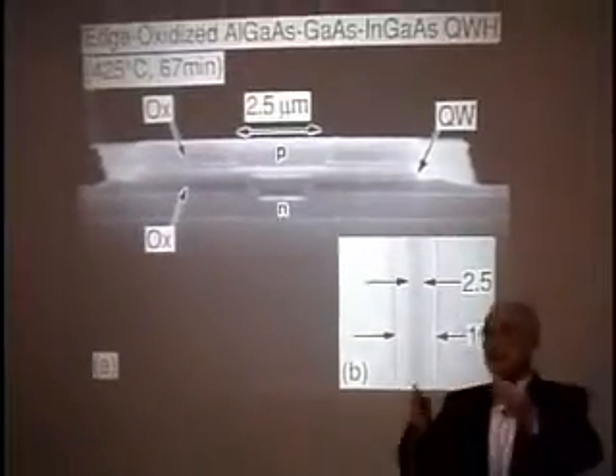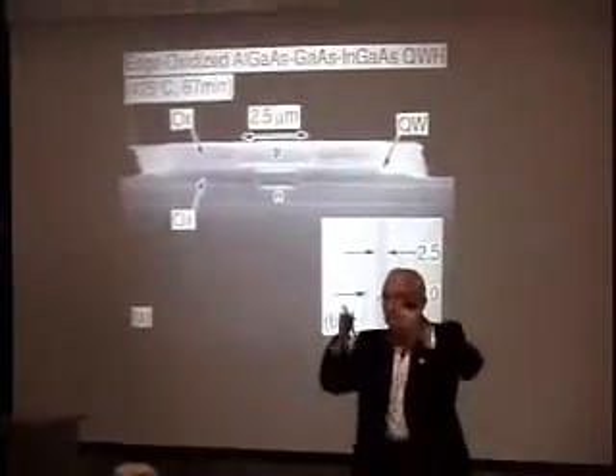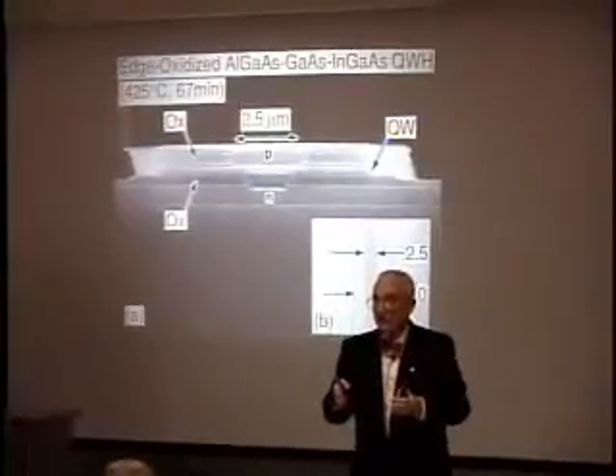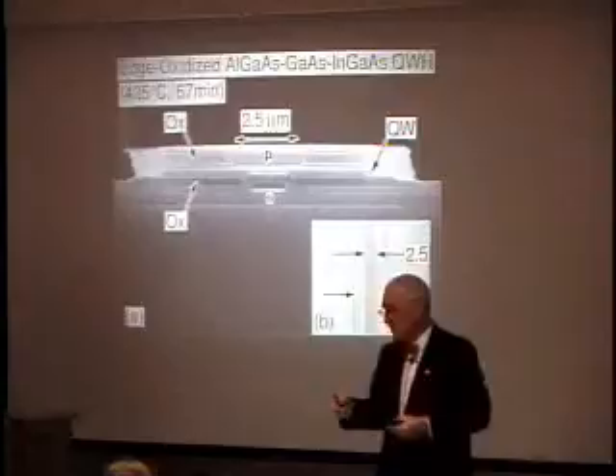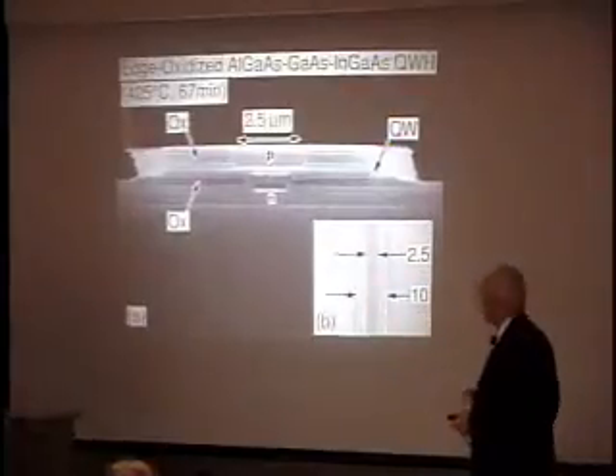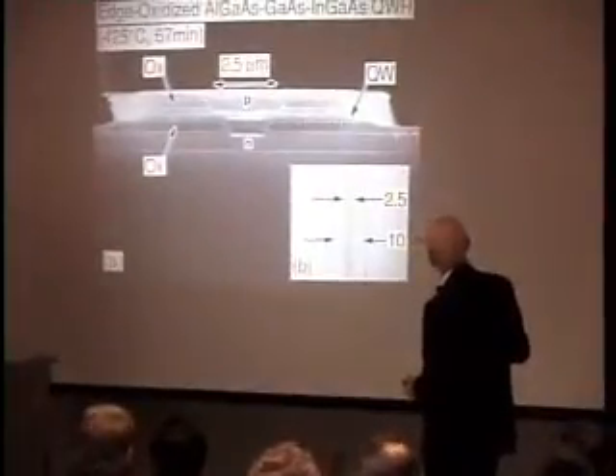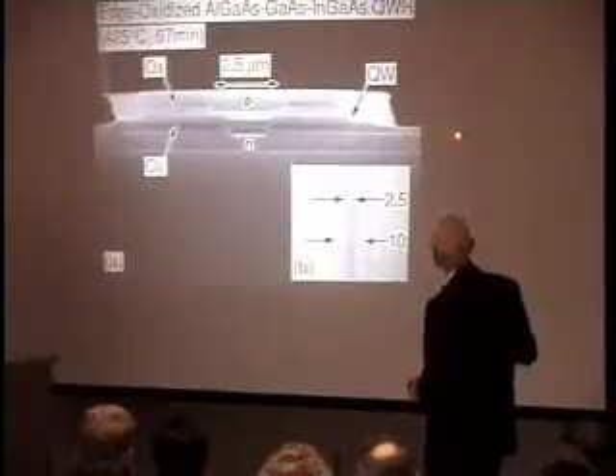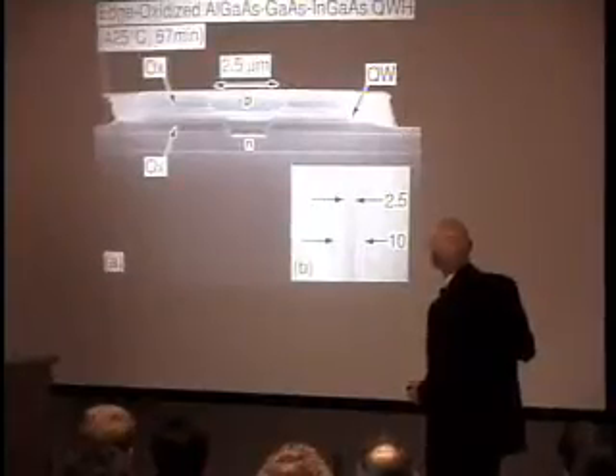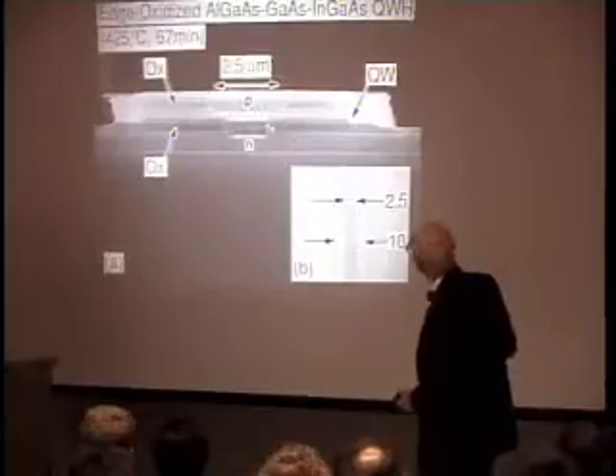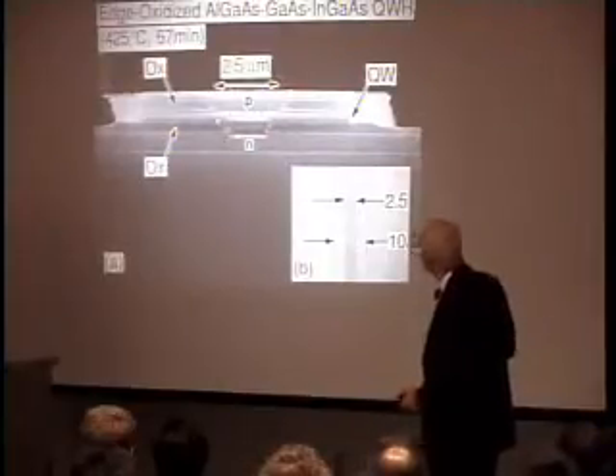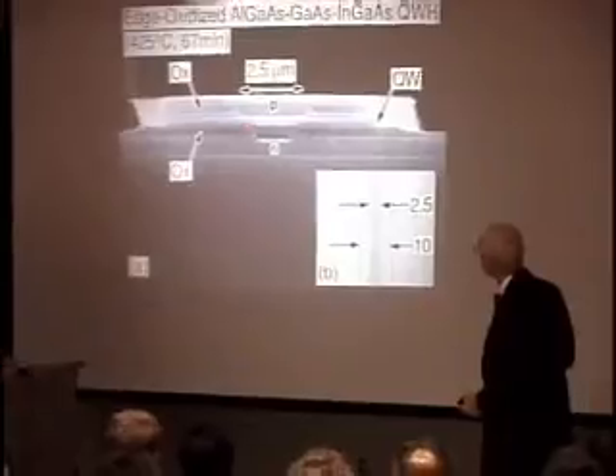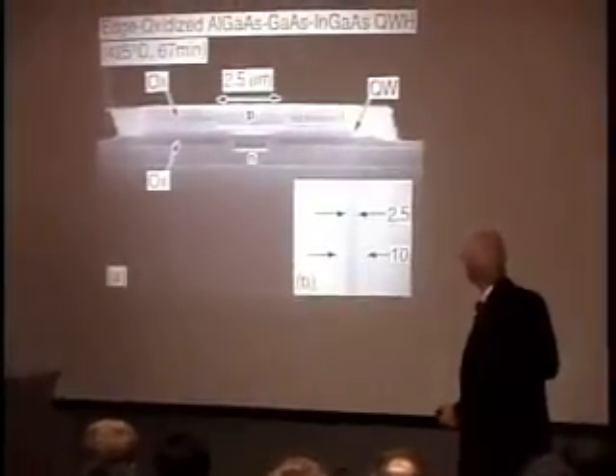So one way to do this is to make your stack that you're going to make lasers out of. You can cut trenches down, or you can cut mesas down, or you can cut wells down and then do your oxidations. And in this particular case, what we did was we cut a mesa on this side and on this side, and from the edge, we left some high composition aluminum gallium arsenide here that oxidized on the surface, and we oxidized inward to here, and inward to here. This is 87% aluminum gallium arsenide. It's a fast oxidizer that came inward this far and inward this far. This is 85% here, which is a slower oxidizer, and it came inward to here and inward to here.